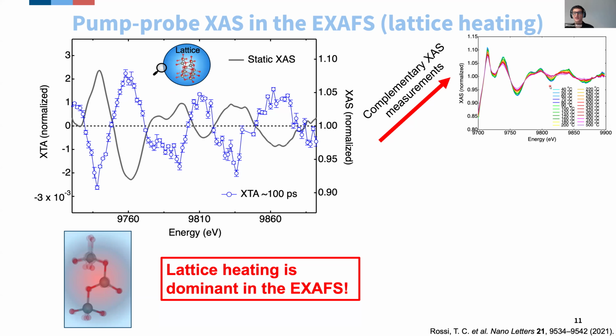And from this database, we are able to simulate what should be the pump-probe signal associated with a lattice when it heats up by a specific amount. So we can do a chi-square minimization, for instance, and try to find the best agreement between this database and our experimental pump-probe data. In this case, we found out that the lattice heats up by 60 Celsius.